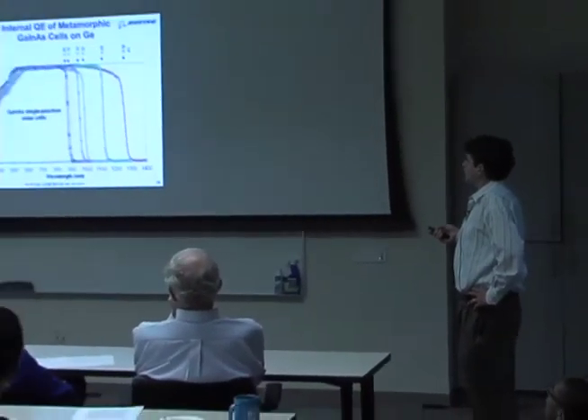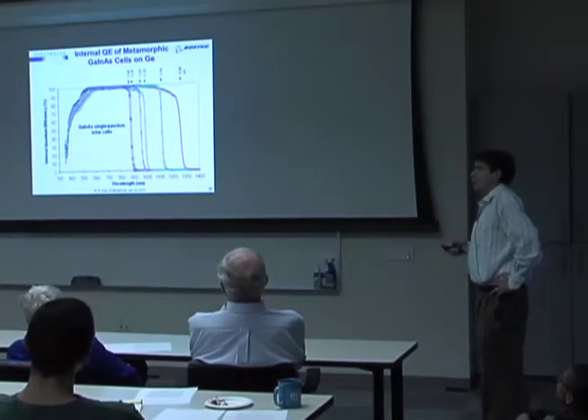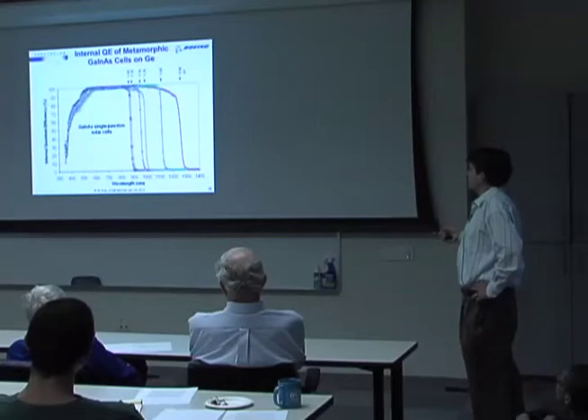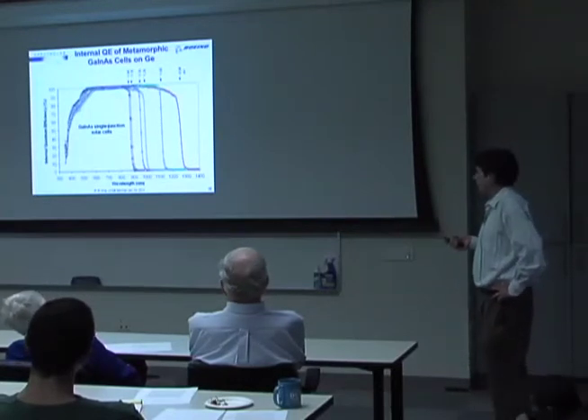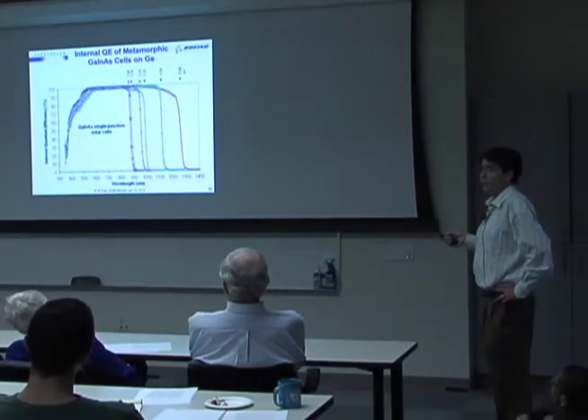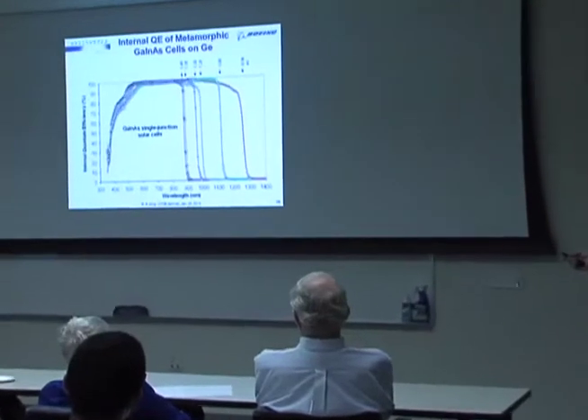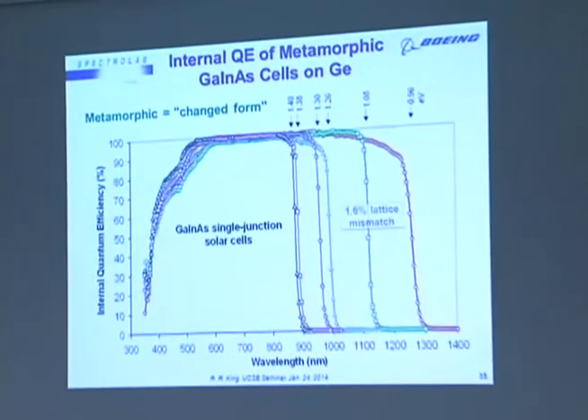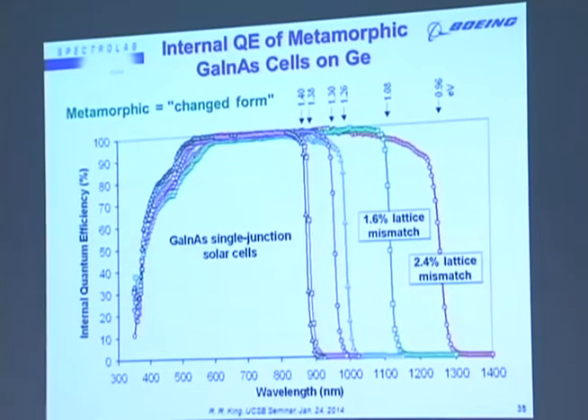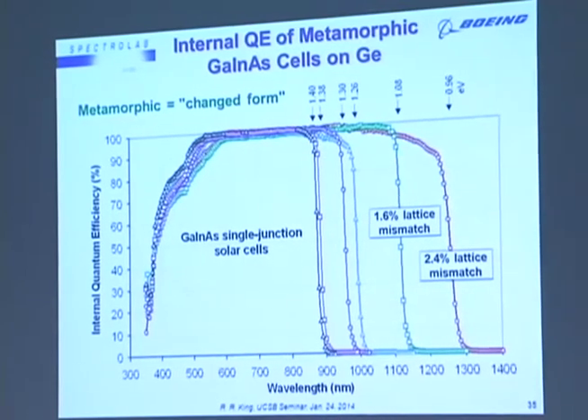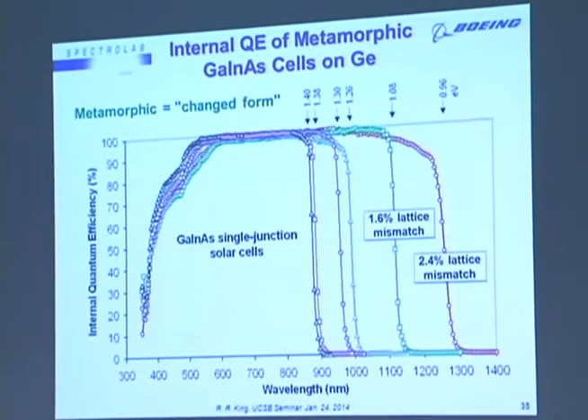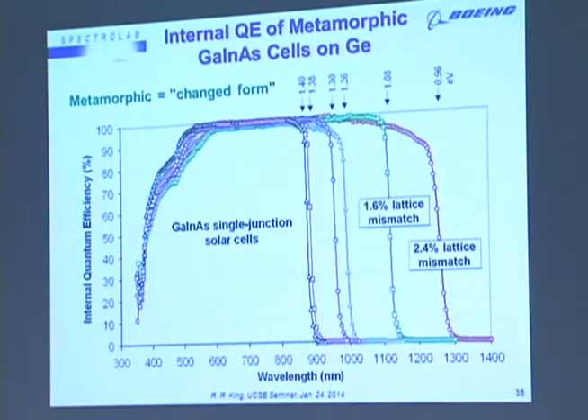And the result of that is we can grow metamorphic solar cells with a wide range of band gaps that retain a fairly high minority carrier collection efficiency out at these longer wavelengths that we need to convert the solar spectrum. So starting with gallium arsenide here at about 1.4 eV, you can see that even when we get out to 1.6% lattice mismatch or over 2% lattice mismatch, which is quite a large amount of lattice mismatch, we're able to get out to 1.1 eV or even below 1 eV and still have quite good minority carrier collection, indicating long diffusion lengths in these metamorphic materials. So it almost gives us the ability to change this band gap at will.